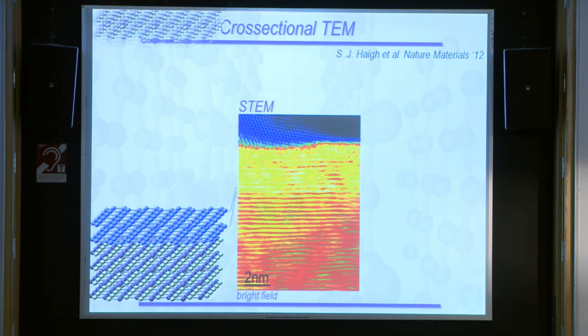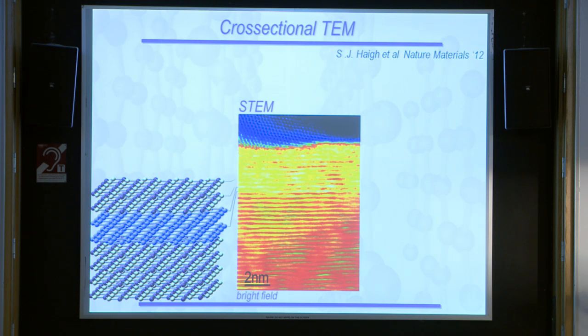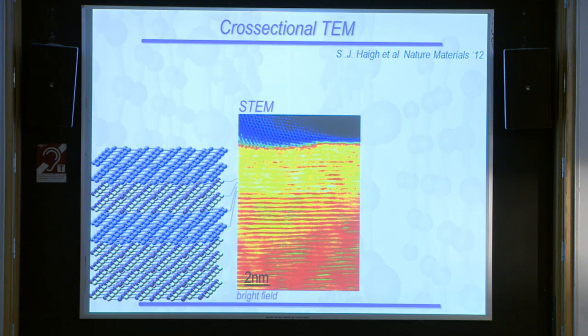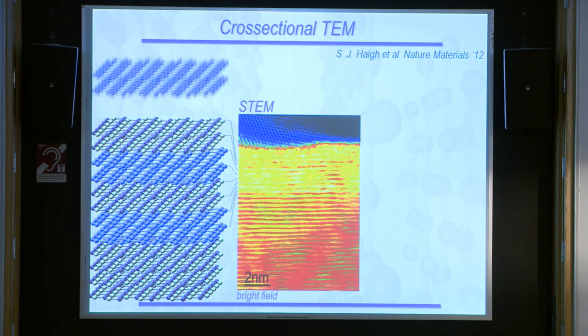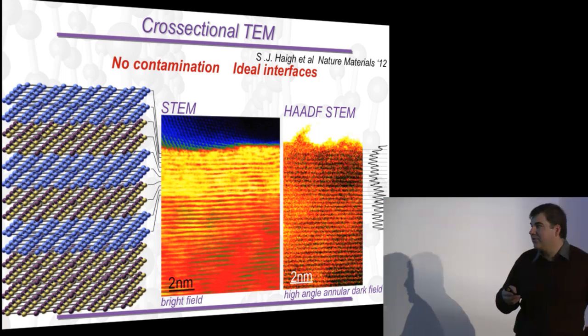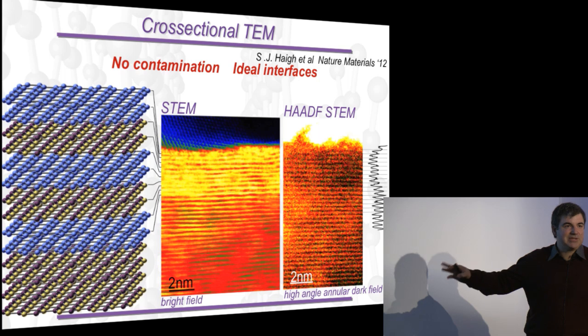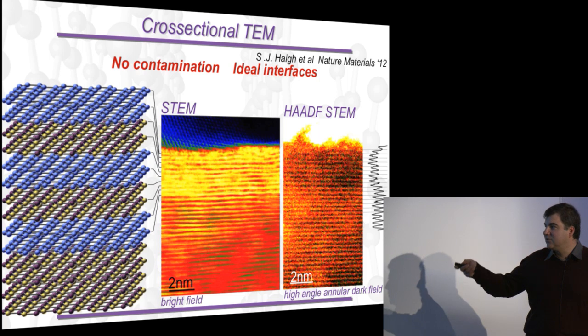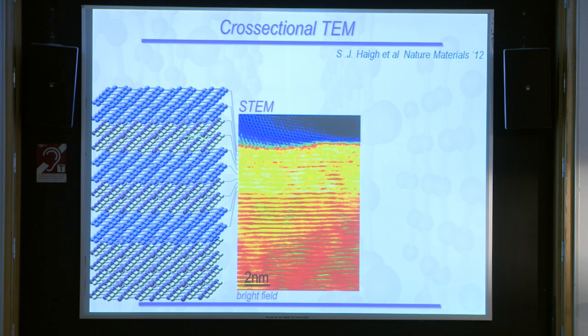Here, what we started with boron nitride, which is a layered material as well. Then we put 2 layers of graphene on top. Then we put 2 layers of boron nitride, and 2 layers of graphene, then 2 layers of boron nitride, and then 2 layers of graphene. Yet it's not just for the sake of impressing anybody. It's an actual device. We studied tunneling, resonant tunneling through this barrier with a quantum well inside.